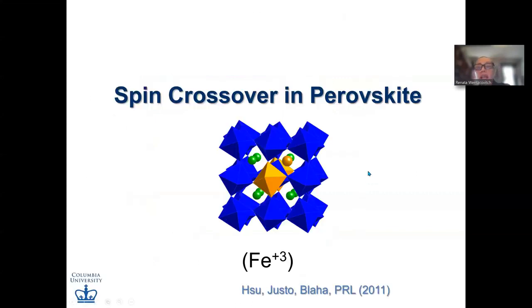So that's it. So what happens in this case here, ferric iron also has a spin state change from high spin to low spin, like ferrous iron in ferropericlase. It's exactly the same situation. And ferric iron here in this site doesn't have a spin state change either. The low spin state here, so this is all the way high spin, five electrons with spin up all the way, no changing electronic configuration. So for the purpose of understanding elasticity of rocks, unless you have ferric iron in the B site, this is not going to be important.